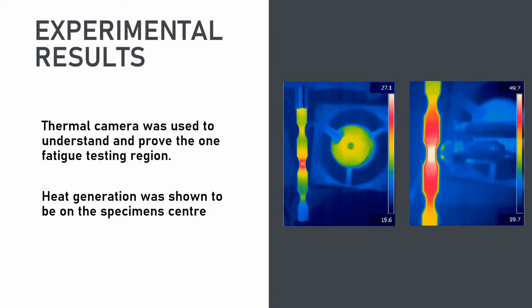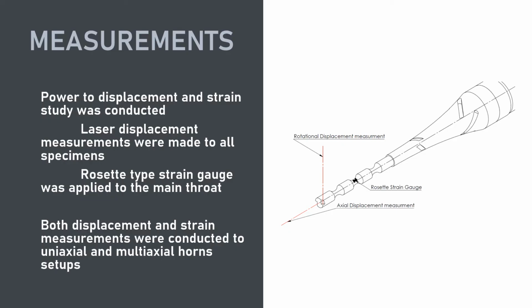Now, in ultrasonic fatigue, the high stress region will have a higher and considerable heat generation. So the first tests conducted, through a thermal camera, proved that indeed we have the highest stress combination in the main throat by having the highest heat generation in the main throat. This can be seen in two different specimens being tested on the image. Now, to better understand and make a complete analysis of the behavior of the specimen, two different lasers were used to measure rotational displacement and actual displacement, and a rosette strain gauge was applied in the main throat of the specimen.